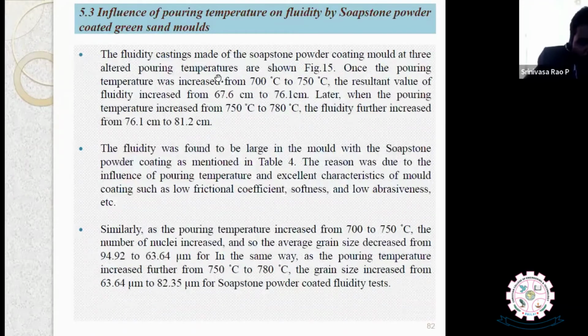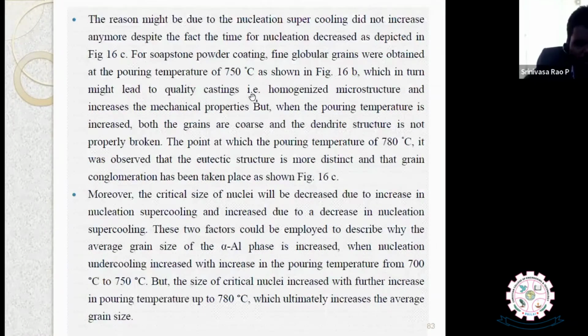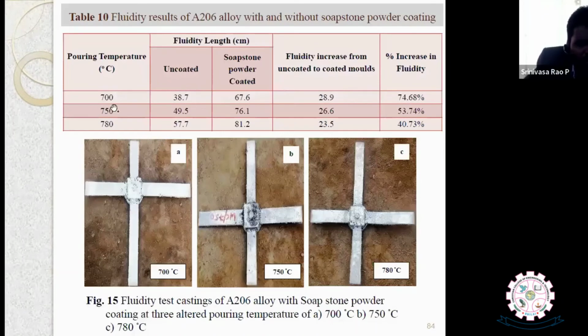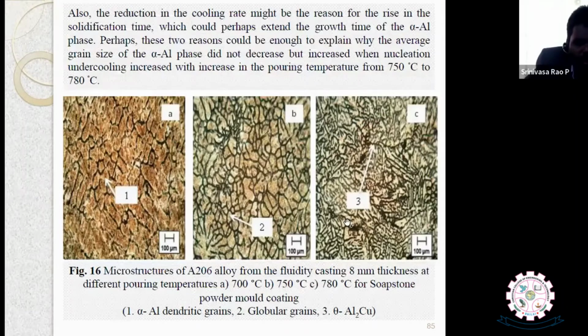Now, the influence of the pouring temperature on the fluidity with soapstone powder coated green sand molds. The soapstone powder coated mold was tested at 3 different temperatures, and the fluidity is further increased from 76.1 centimeters to 81.2. The table is given here. Okay, so 700, uncoated and soapstone powder. The percentage increase in fluidity is this much. So the best composition that we have got